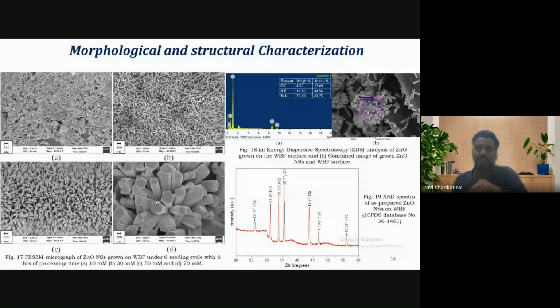We also varied the number of seeding cycles and the hours of growth duration. After that, we got the optimized, favorable values of the seeding cycle and processing time, which are 6 seeding cycles and 6 hours of processing time, with a different set of molar concentrations. Overall, 70 millimole concentration is better. Beyond 70 millimole, there was a chance of agglomeration because of the high quantity of zinc salt inside the solution.